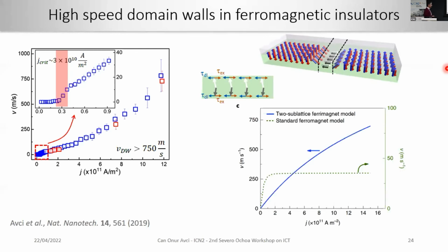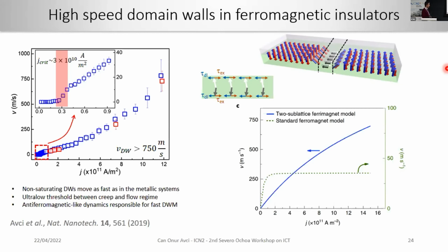And due to that, we do not observe a saturation of the domain wall velocity, because in this physics, if you had only one sublattice, just one magnetization direction, then it would quickly saturate, and you would have no further enhancement of the domain wall velocity. But because of this exchange coupling enabled by the ferrimagnetic character, you have non-saturating, extremely large velocity of domain walls in these materials.